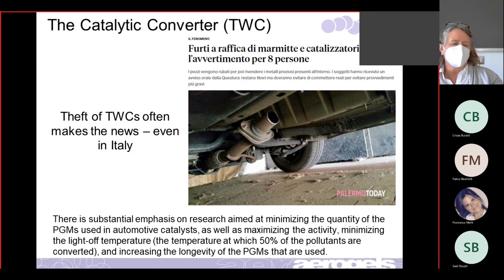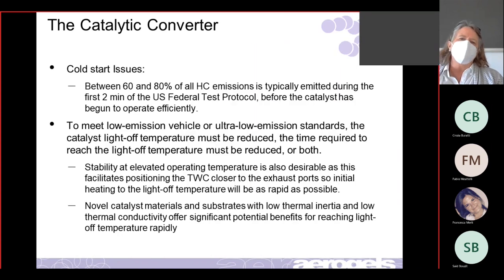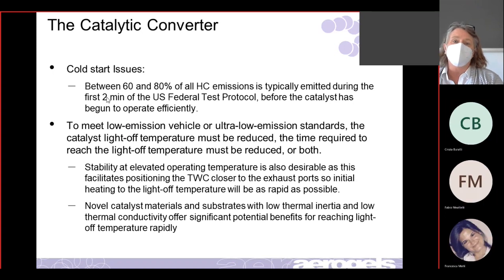Other issues with the catalytic converter are that between 60 and 80% of the hydrocarbon emission is usually emitted during the first 2 minutes. So when you start the car, the catalytic converter is cold, it's a cold start, and it doesn't act efficiently. So the pollutants just go through, you're not converting anything. So in order to meet low emission or ultra low emission standards, it's necessary to try to reduce that light-off temperature or the time required to reach light-off, or both. If this thing heats up within 30 seconds, that's great. Or if instead of having to reach 200 degrees C, we started converting at 100 degrees C, that would be better. So either of these.